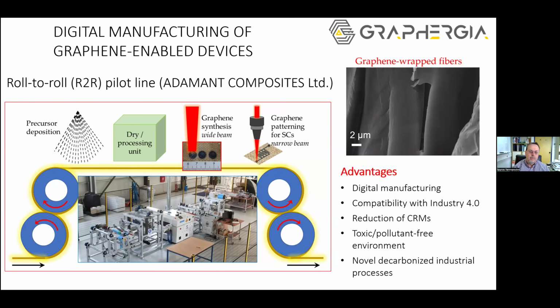Actually, one of the most important practical dimensions of our project is digital manufacturing. So this slide shows a picture from a roll-to-roll pilot line we're developing in collaboration with Adamant Composites, an SME located very close to our Institute, where you can see that this line combines precursor deposition, dry processing, graphene growth by laser patterning of the precursor. And this is a very important step because it brings graphene-enabled devices very close to scalable industrial implementation.